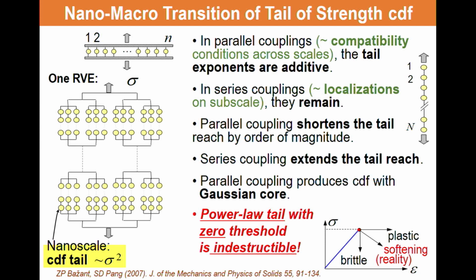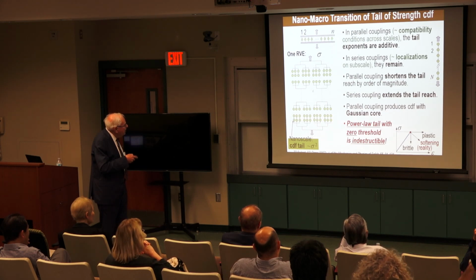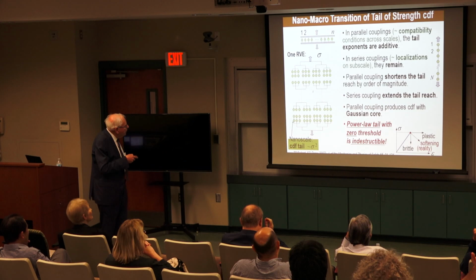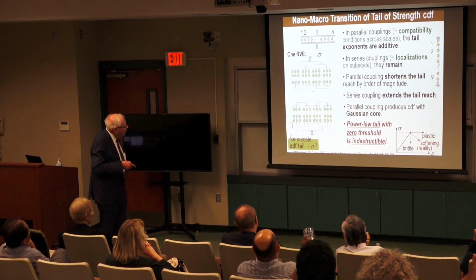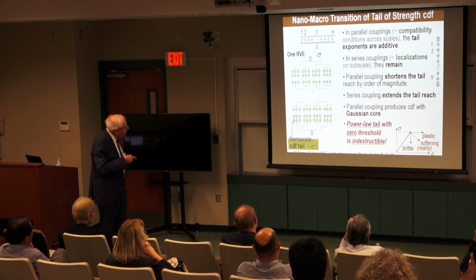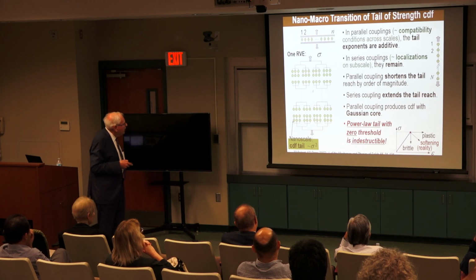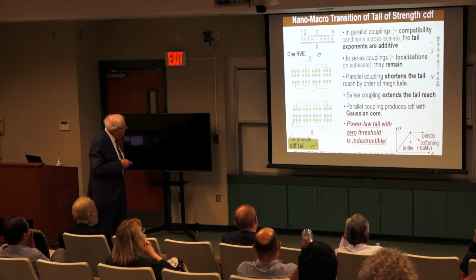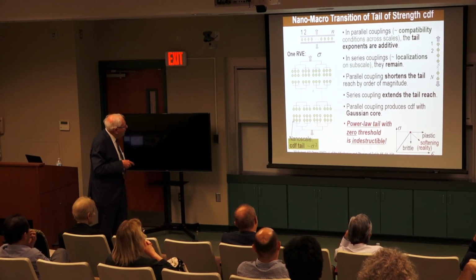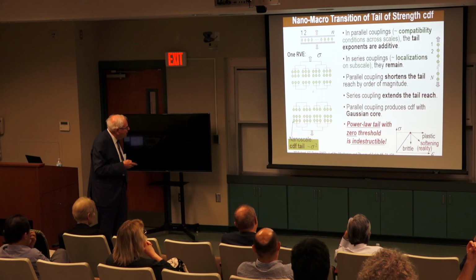So this is one model which we simulated and calculated, that you have various types of series and parallel couplings, and what has been shown, it takes a lot of asymptotic calculations, Laplace transform, but it has been proven that power law is always preserved by these systems, and in parallel coupling the exponent is raised but additively. So one element here is tail exponent 2, 2 have 4, 3 have 6, and so forth, and in a chain they are preserved, but penetration of the power law tail changes in the opposite way, and the only possible way to explain what we see is that it's alternating series and parallel connections. Many connections series, many parallel, and that's how we can explain what we see on a larger scale.